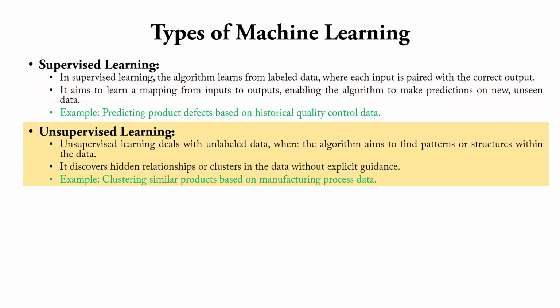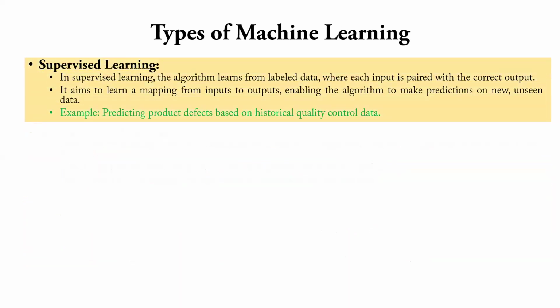In supervised learning, the algorithms learn from labeled data. That means we give our data input and output as labeled data. Here, my input parameters are the variation of silicon carbide in aluminum, how the compaction process in powder metallurgy affects the tensile strength, and how sintering temperature and time affect the tensile strength. From our lab, we gathered data over 1 year. We have 172 data points, with labeled data of tensile strength. That is the quality of the data.